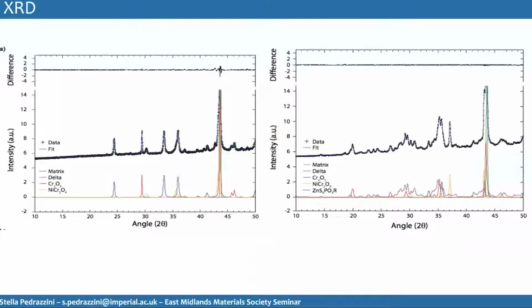But then the XRD, in this case, gave us a bit more of a solution to the problem. So this is comparing the outer surface on the left with the inner surface on the right. We have the same sort of matrix superalloy, some delta phase precipitation, chromia, the nickel chrome spinel as expected. But on the inner surface, we have something that's a fuel additive. So it's actually a deposit of a fuel additive that built up on the surface.